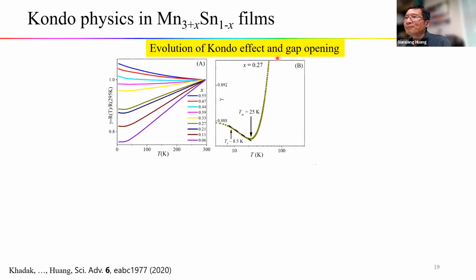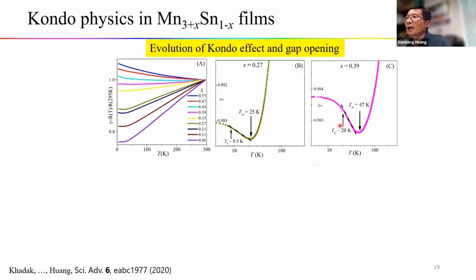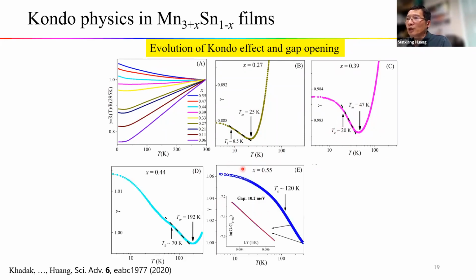If we zoom in for this x equal to 0.27, we see the resistance minimum around 25 Kelvin. By careful analysis, we can get the Kondo temperature is about 8.5 Kelvin. Further increasing the doping increases the Kondo temperature. At the high doping range, we see this insulating behavior. By careful analysis, we obtain a Kondo gap value of about 10 meV.